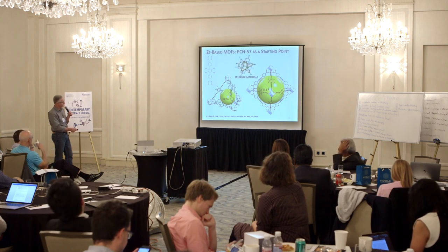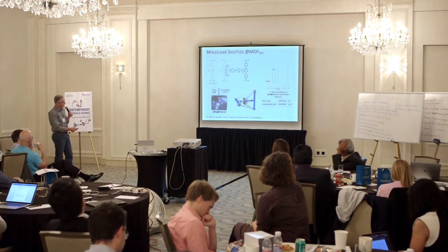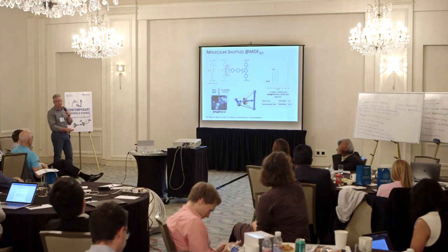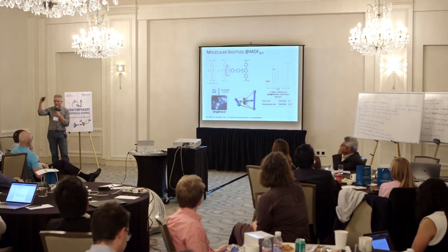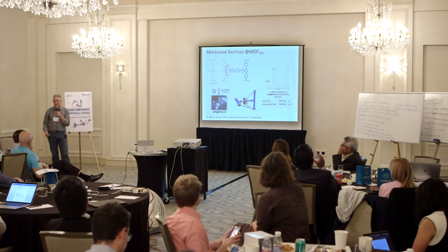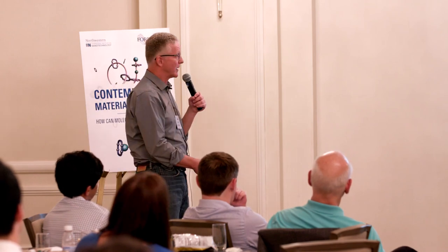And it turns out that a crossbar with two phenyl rings will span right across here, between there and there. So that's the perfect distance. So what we're going to do is make a material that's not made out of one linker but two. One of these linkers is going to be a molecular shuttle, and the other is going to be either the one I just showed you with four methyl groups, or one with four nitrogen groups, or just four CH groups. And the interesting part here that makes this another level of sophistication is we can make all three of these materials, and the shuttling is different in all three of them. So we're trying to think about why that's happening.